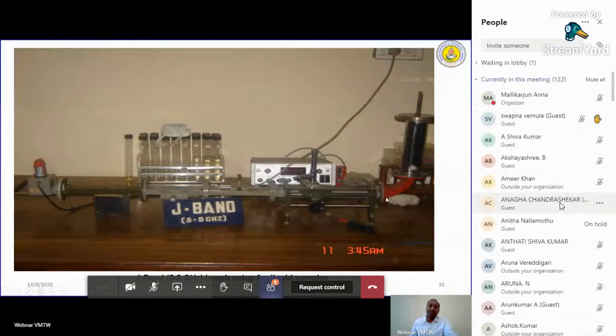Once the machine is on, you have to continue the run. If there are any power fluctuations, this magnetron may change the power, and the source is also disturbed. Due to that, you may not get the same frequency as the first point. Second, you have to keep it on continuously, take the values, then plot it. When I was measuring this, I had to sit 24 hours continuously to do this measurement for that particular composition.